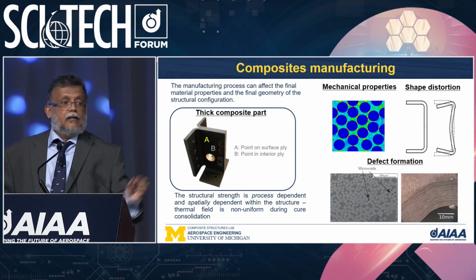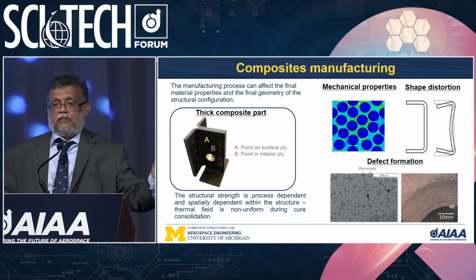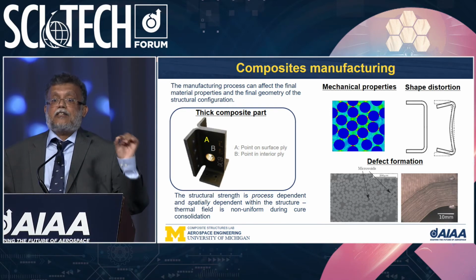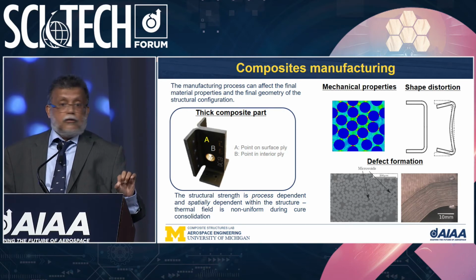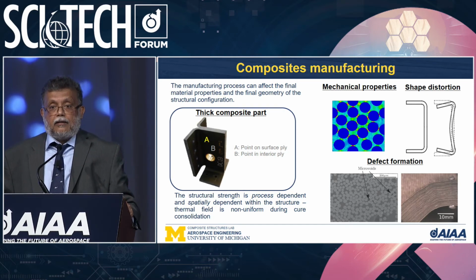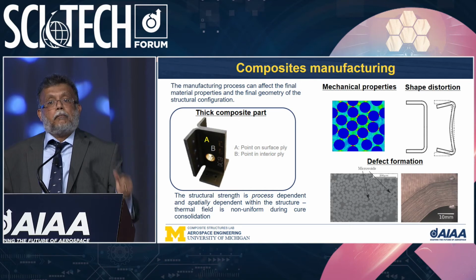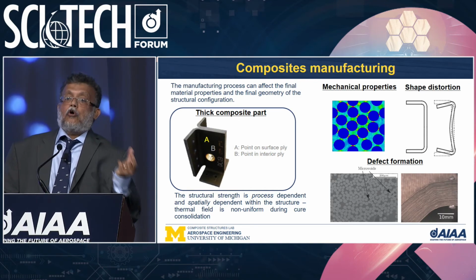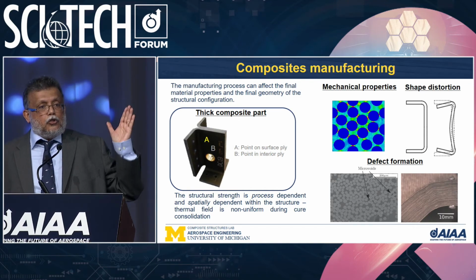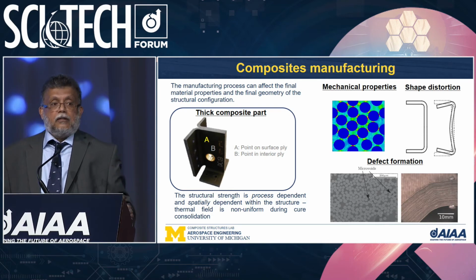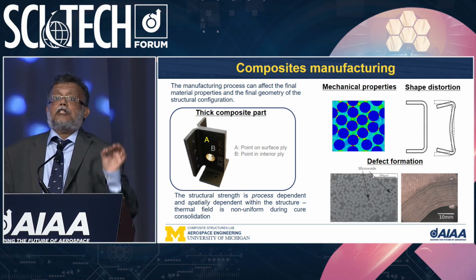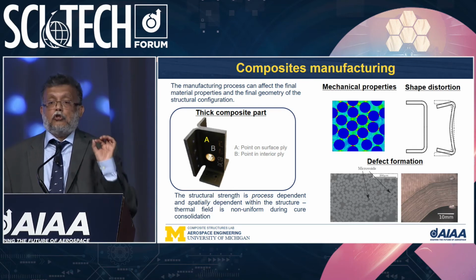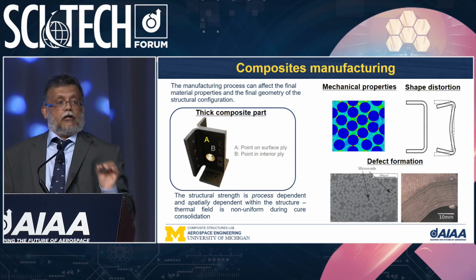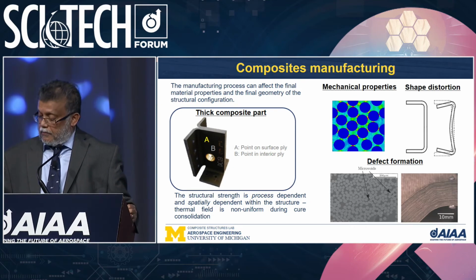As a result, the strength on the surface is not the same as the strength in the interior. Not because the fibers are at a different angle, it's because of the thickness of the part. So when you cook a thick part, you have a temperature distribution resulting in a strength distribution, which you have to account for to accurately capture progressive failure.